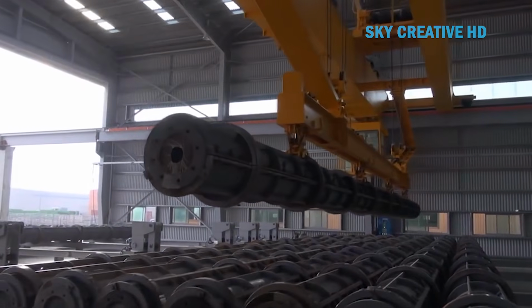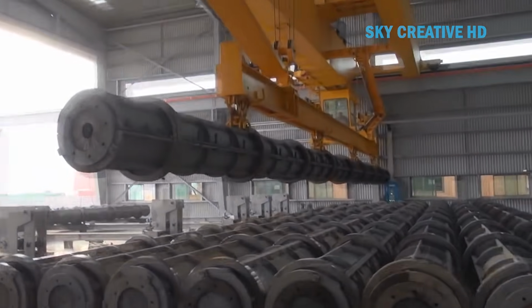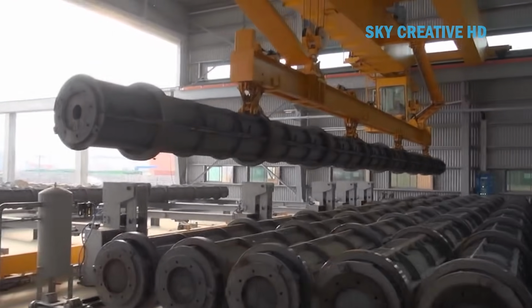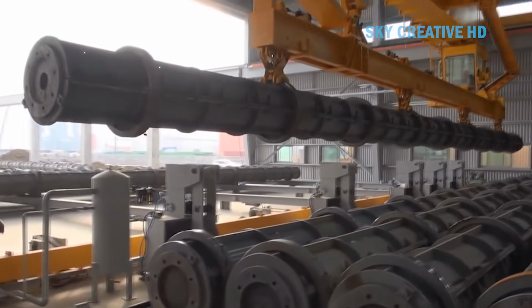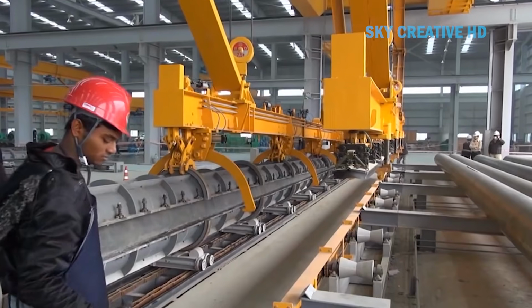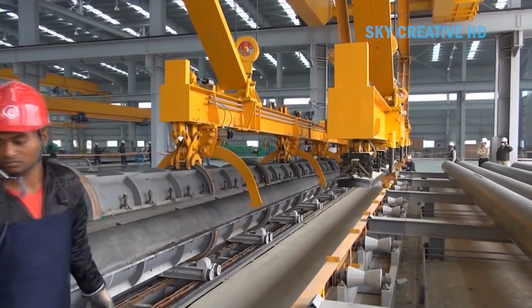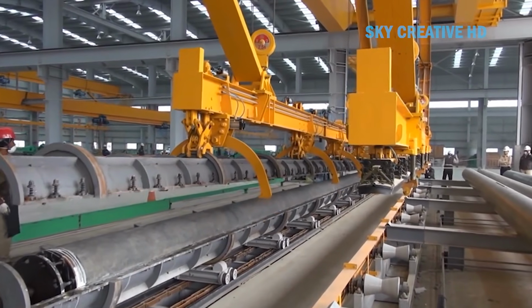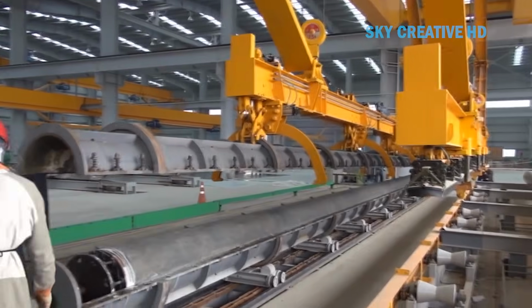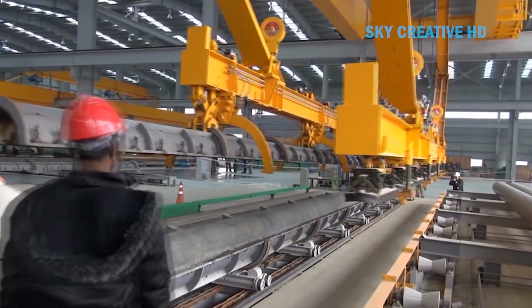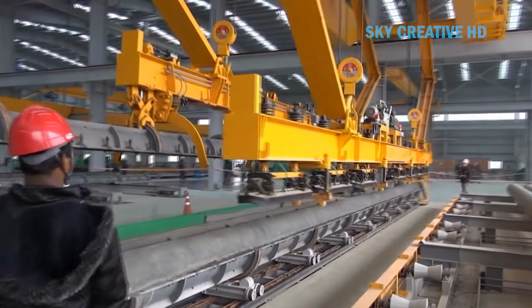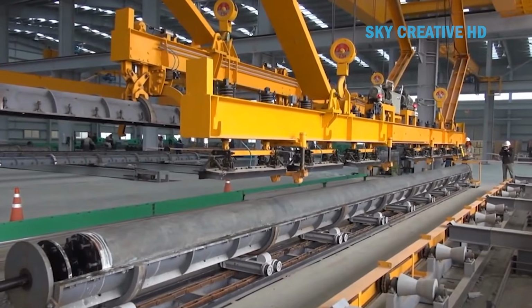Steam chambers maintain temperatures around 140 degrees Fahrenheit while keeping humidity at 100%. This accelerated curing allows the concrete to achieve in hours what would normally take weeks of natural curing. The demolding and final processing stages reveal the finished product, perfectly straight, uniformly colored concrete piles with strength properties that would amaze the concrete pioneers of the early 1900s.